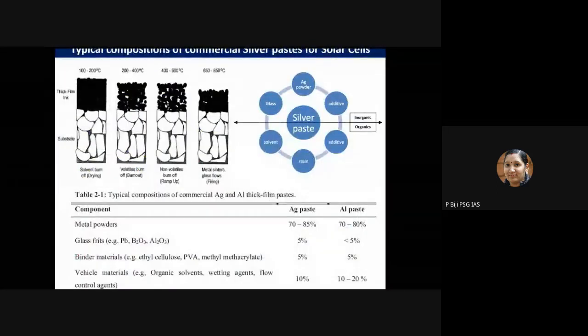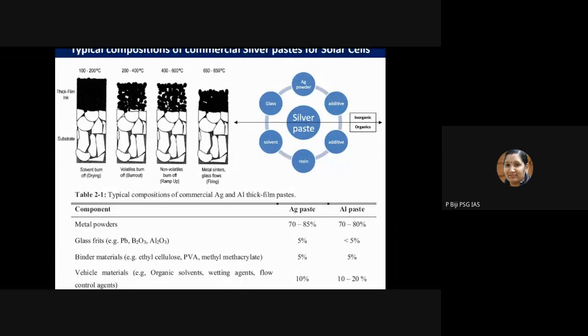Then after that, up to 850 degrees Celsius, they will sinter. During this time, the metal starts to sinter and the glass frit is there. So there are glass materials, and that glass flows through these voids, which can actually assist the addition of the metal lines.